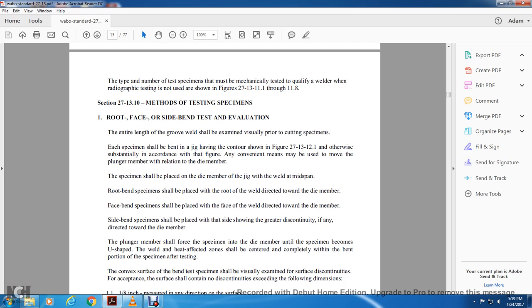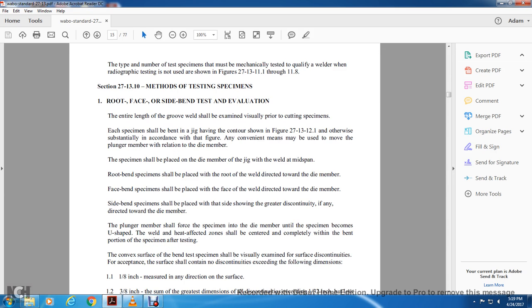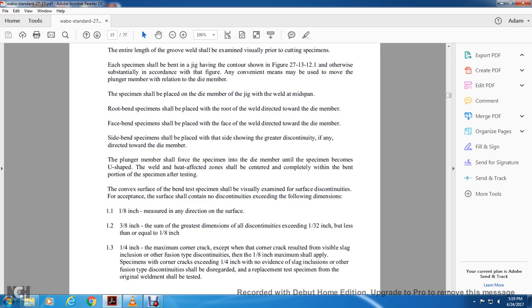The side bend specimen shall be placed with the side showing the greatest discontinuity, if any, directed toward the die member. The plunger member shall be forced into the die member until the specimen becomes U-shaped. The weld and heat affected zone shall be centered and completely within the bent portion of the specimen after testing. The convex surface of the bent specimen shall be visually examined for surface discontinuities. For acceptance, the surface shall contain no discontinuity exceeding the following dimensions: